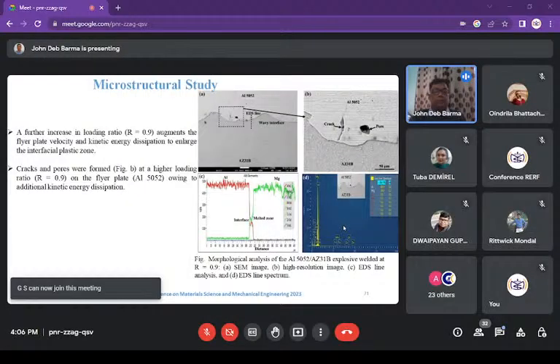So, and if you look at figure D, the EDS line spectrum, as you can see here, it shows that the major constituents of this aluminum 5052 and AZ31B welded interface are, I mean, more aluminum is present, that is 60.4%, and magnesium is near about 38.5%, which are coherent also with the XRD result that we have done. So here from these discussions, we can say that the concentration of the weaker parent alloy, here the weaker parent alloy is the aluminum 5052, at the interface is higher, which led to the degrading of the bonding strength, which is congruent also with the tensile result. Okay.